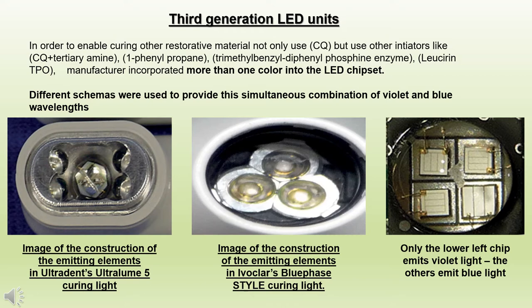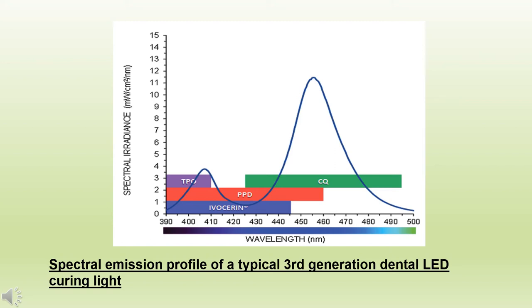Different schemas were used to provide the simultaneous combination of violet and blue wavelengths. One solution utilized a strong, centrally positioned, high-wattage blue LED surrounded by four lower-powered, converging violet LEDs. This arrangement is seen in the figure. LEDs deliver a narrow range of wavelengths, with many of them not emitting light below 420 nanometers. When using a single peak LED, any initiators which need wavelengths below 420 nanometers are not activated. Multi-peak LEDs deliver light below 420 nanometers, which should effectively activate all other commonly used photoinitiators.